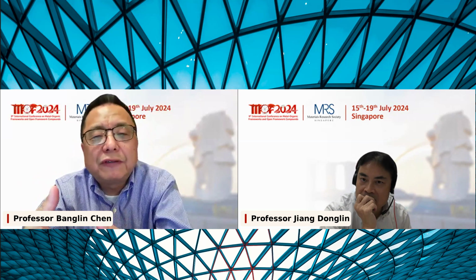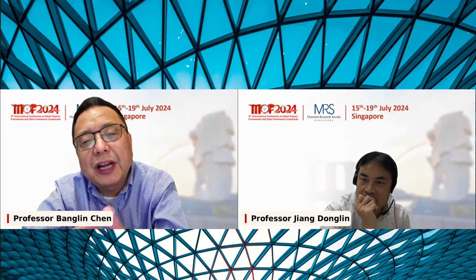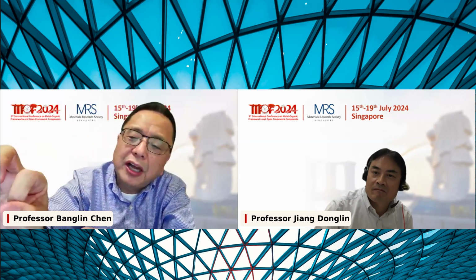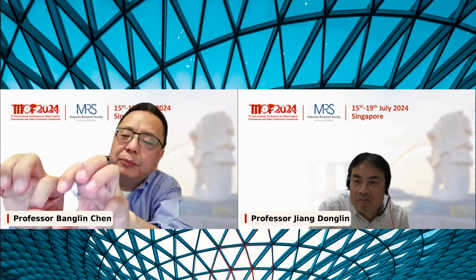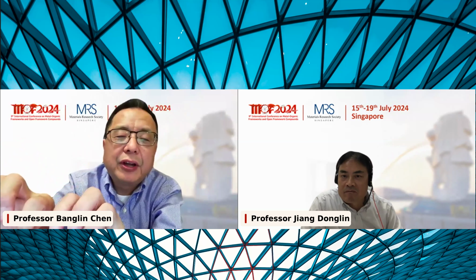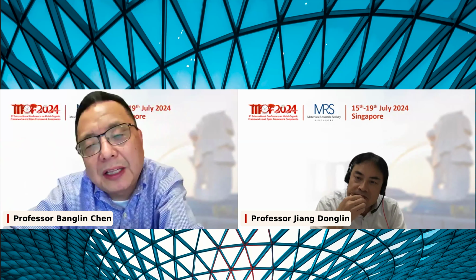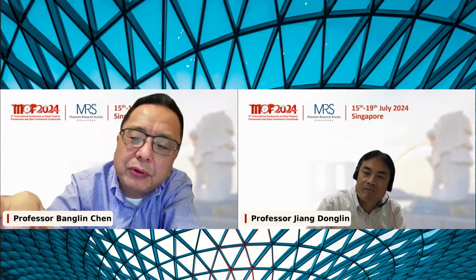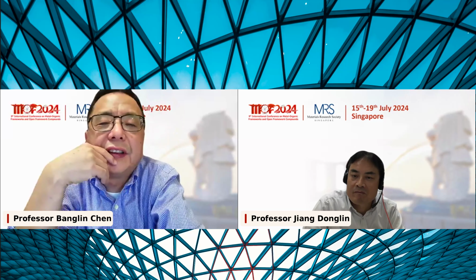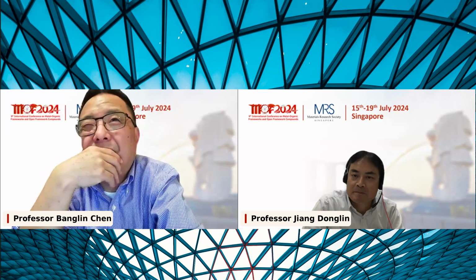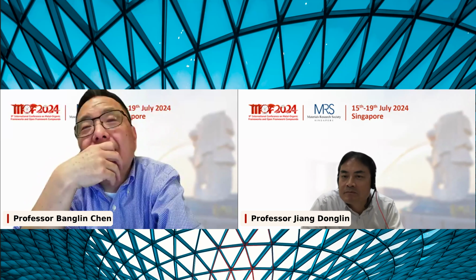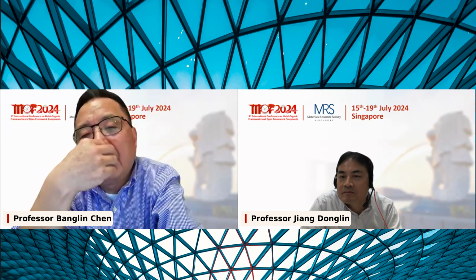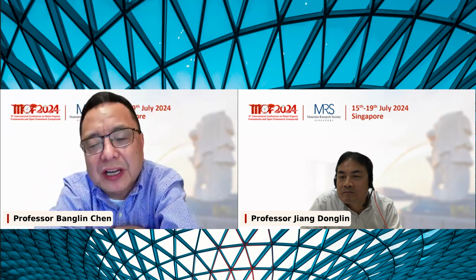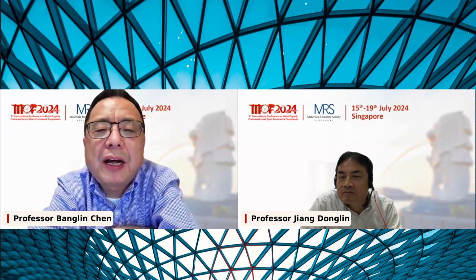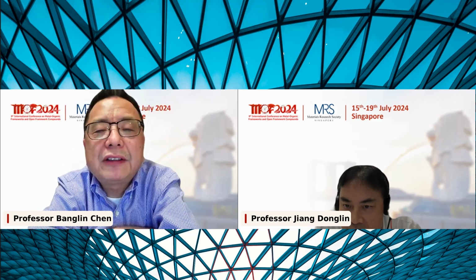So in order to develop this kind of high performance material, the ideal one will have a small window and a suitably large pore space. So maybe use the pore space to take up a large amount of gas molecules and use these pore windows for the sieving separations. And for the organic linker, of course, we know the amine will have a little bit stronger interaction with carbon dioxide on the organic part. But it's still very challenging.